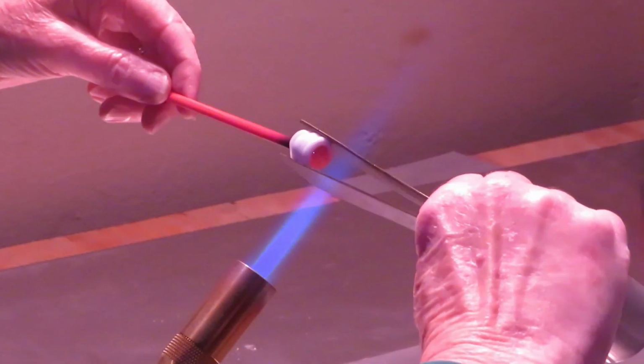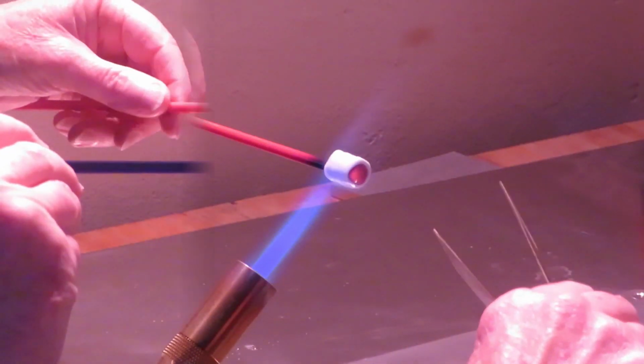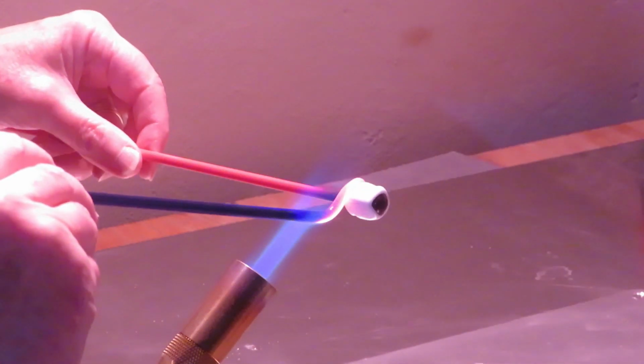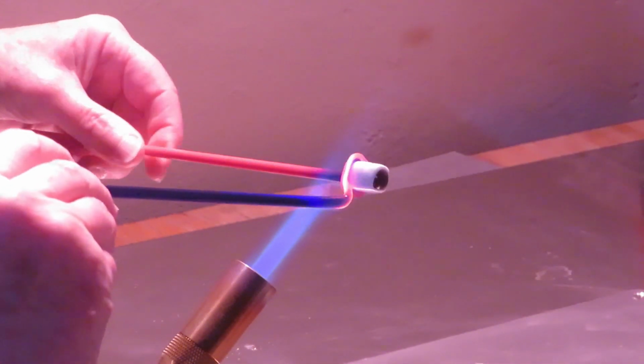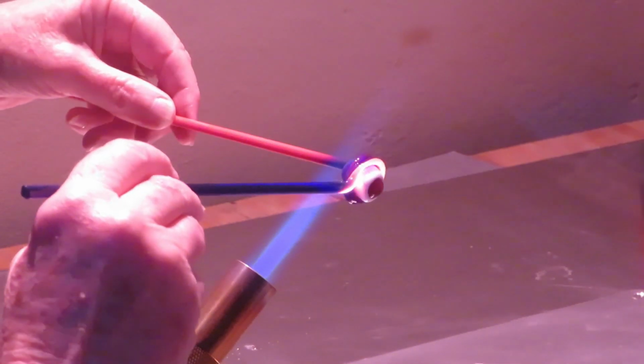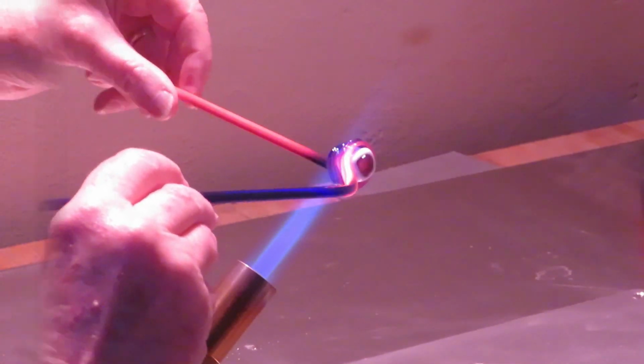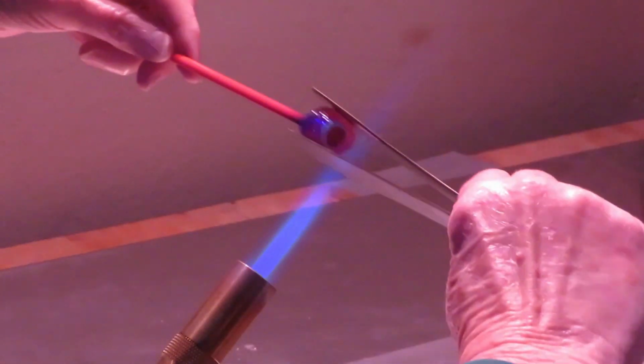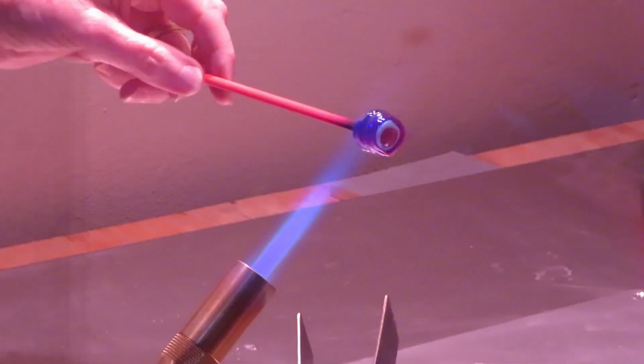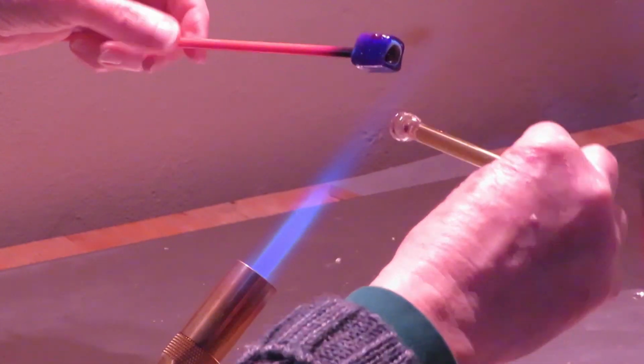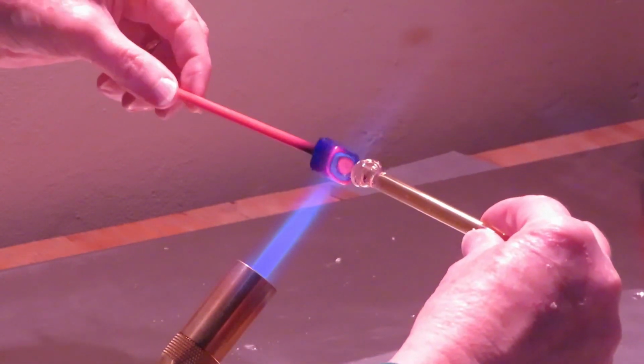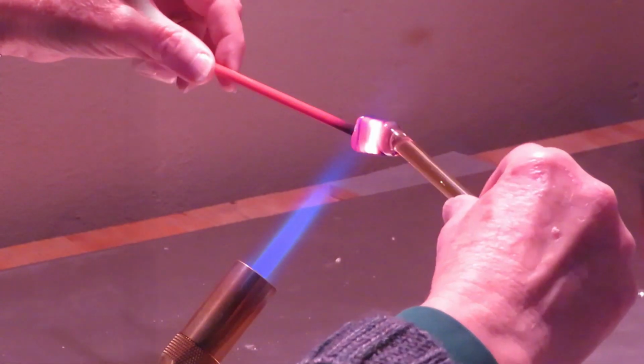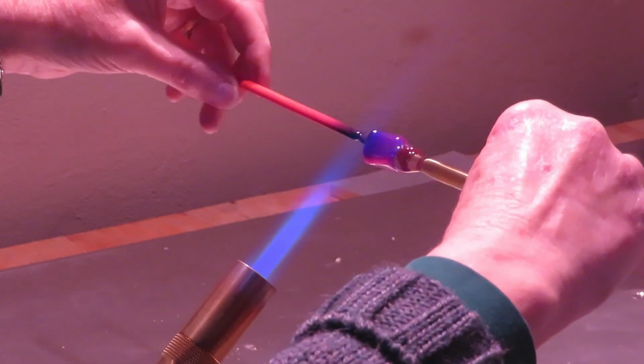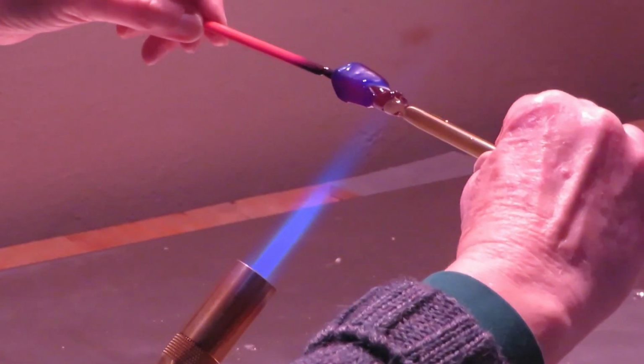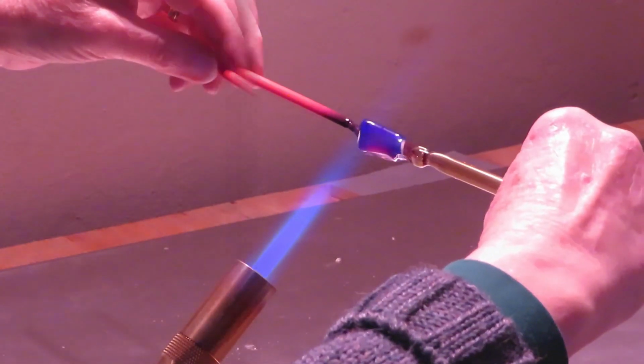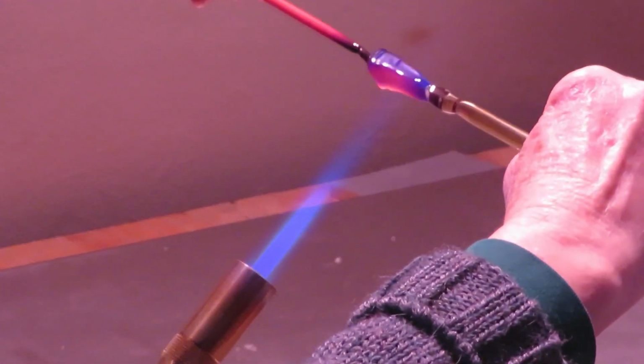The glass is tonged to consolidate. Next, dark blue translucent glass is wrapped round the white. The mass is further tonged and shaped into a square cross-section, ready for pulling into a longer cane. A clear rod is attached to the free end of the cane and the whole is heated and then pulled to elongate it. The cross-section becomes thinner and the cane much longer during this process.